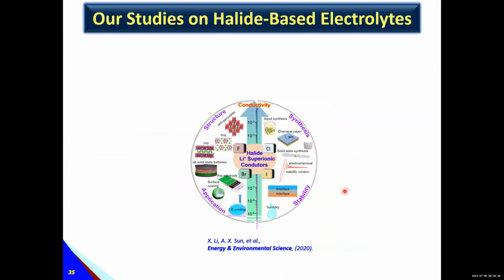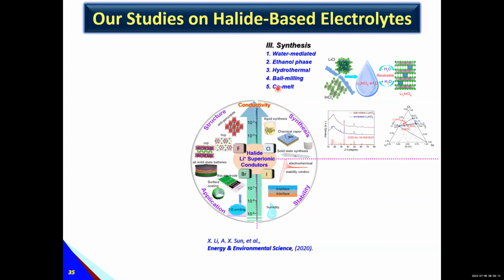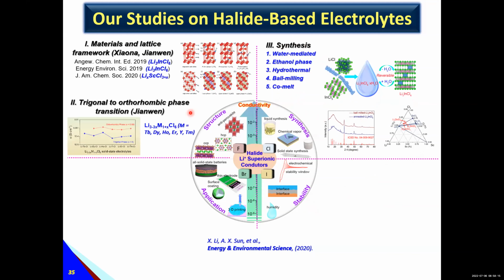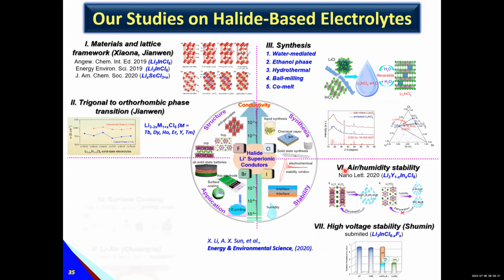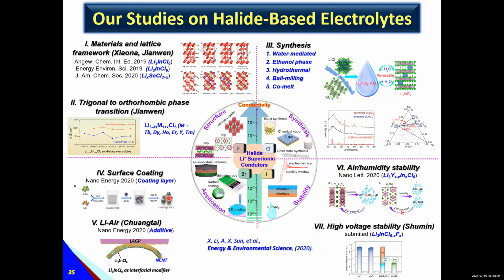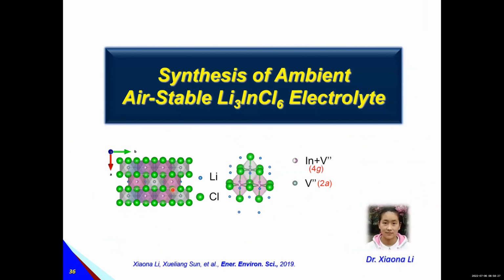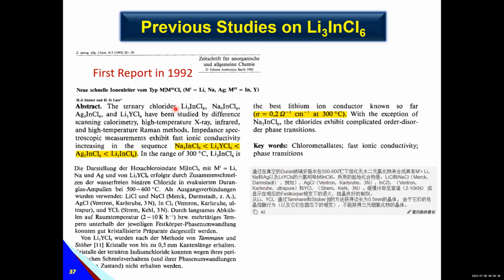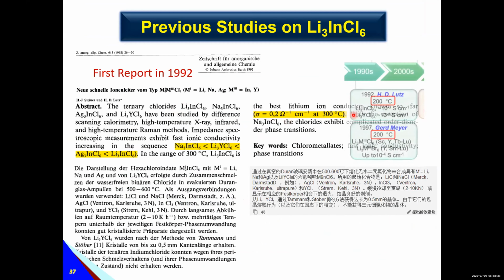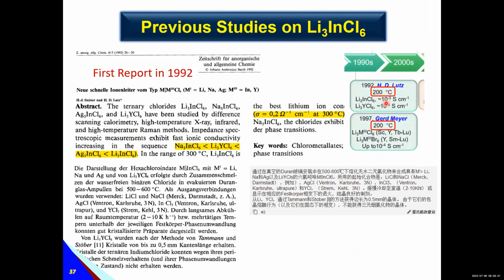So in this part our group works on synthesis, structure control, stability, and application. For example, we try to develop different approaches to synthesize, control the structure, have good ionic conductivity and air stability, and also use it for different systems. So I give an example, lithium indium chloride. We work on that because we found that in the first report many years ago the ionic conductivity was very low. At 200 degrees C, they have ionic conductivity. At room temperature, they don't have good ionic conductivity.